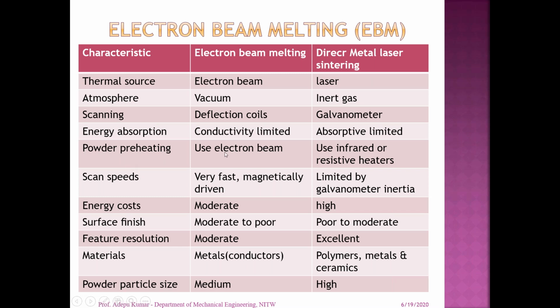So here, powder preheating uses the electron beam, or infrared or resistive heaters. The scan speeds are very fast, magnetically driven, with limited inertia, versus galvanometer inertia. Energy cost is moderate in one case and high in the other. Then surface finish is poor, versus poor to moderate. Then feature resolution is moderate versus excellent. Conductive metals can be processed with electron beam as a source, whereas here metals, polymers and ceramics can be processed, only highly reflective materials are not possible with a laser as a power source. The powder particle size here is medium, and here you can go with medium, high or low.